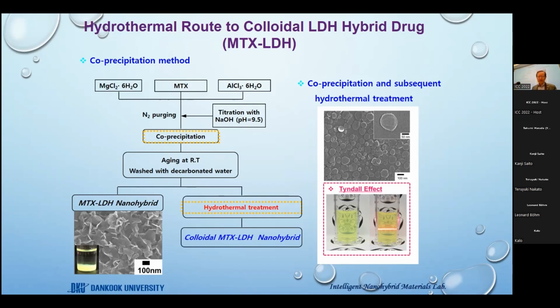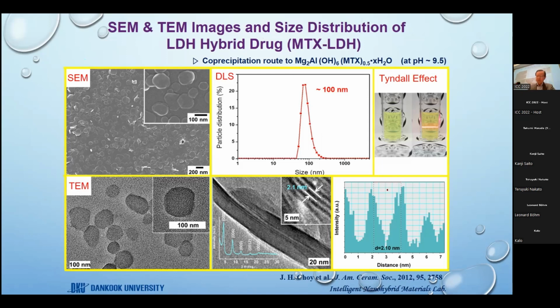There is a very tricky technique there to get the colloid from the precipitate. It is very important to control the surface charge upon the hydrothermal reactions. Well, according to the XRD patterns of MTX LDH, the basal spacing of LDH was expanded from 7.69 angstrom to 21 angstrom upon intercalation of MTX into the LDH layer.